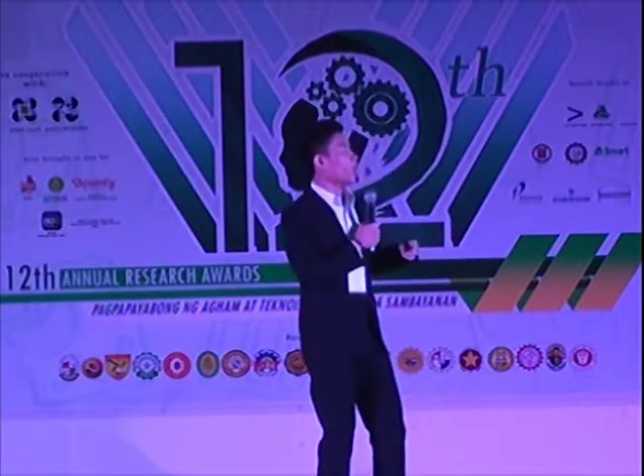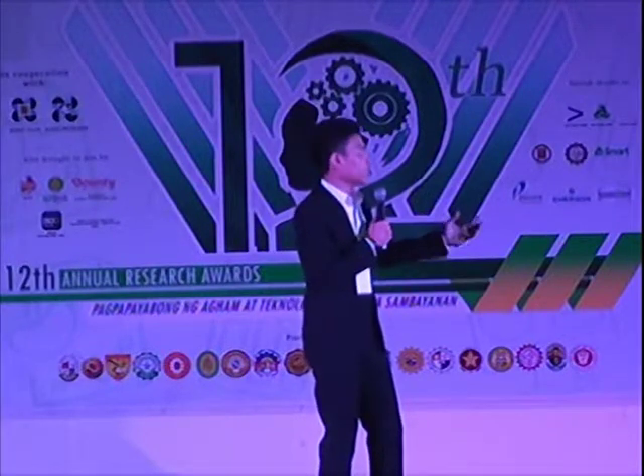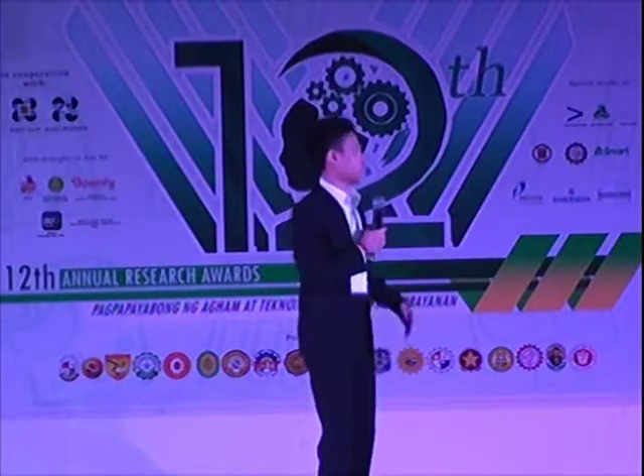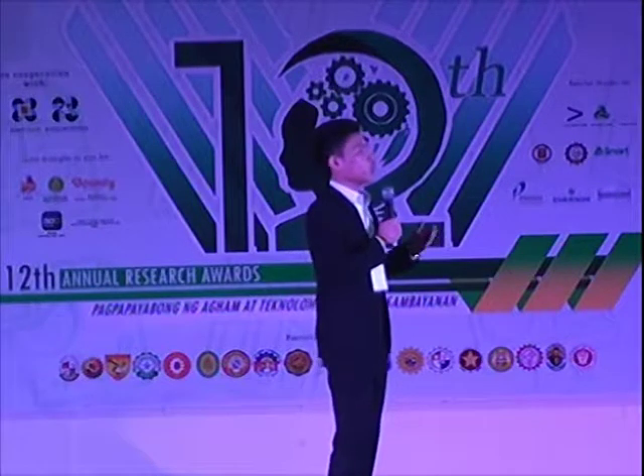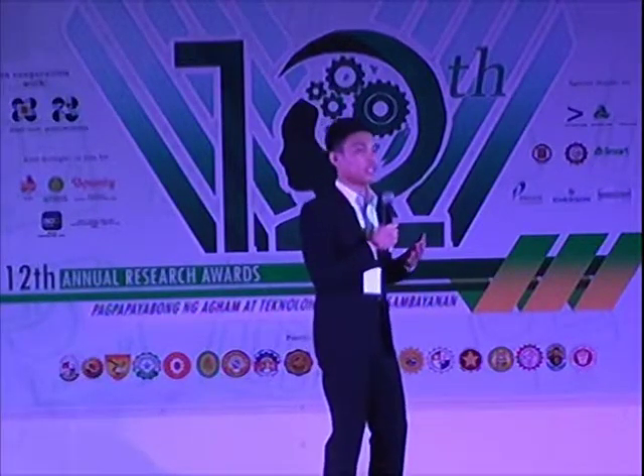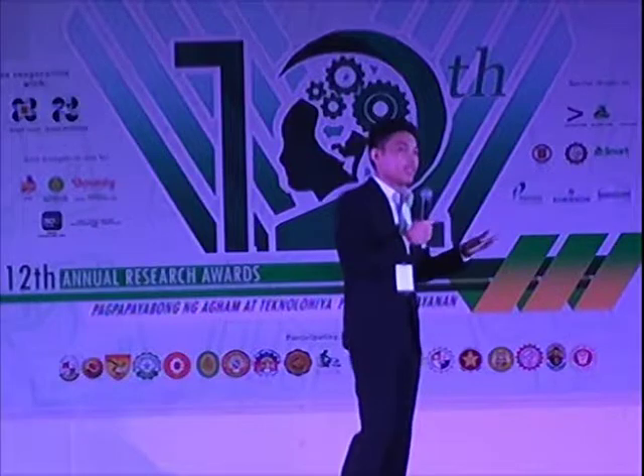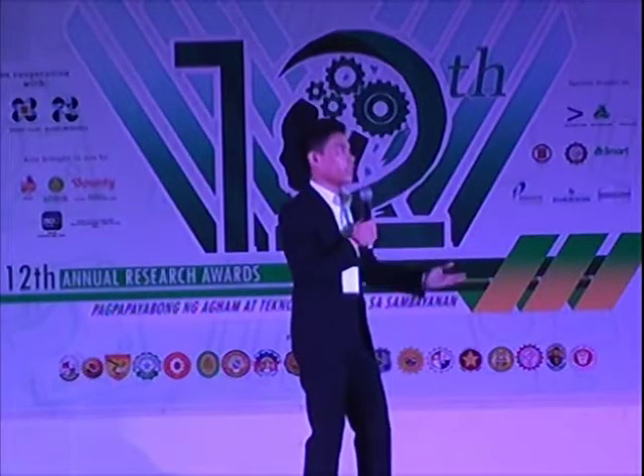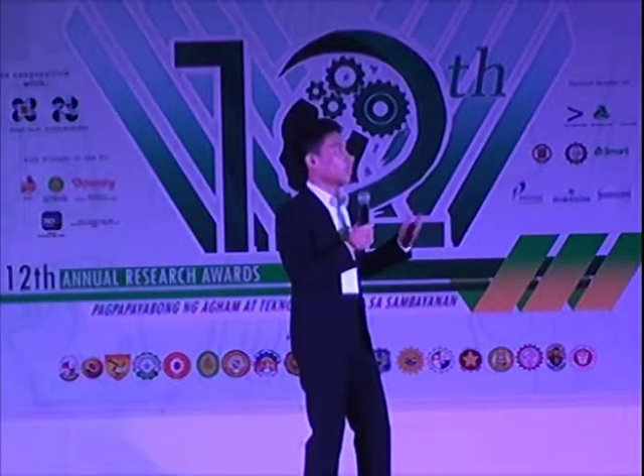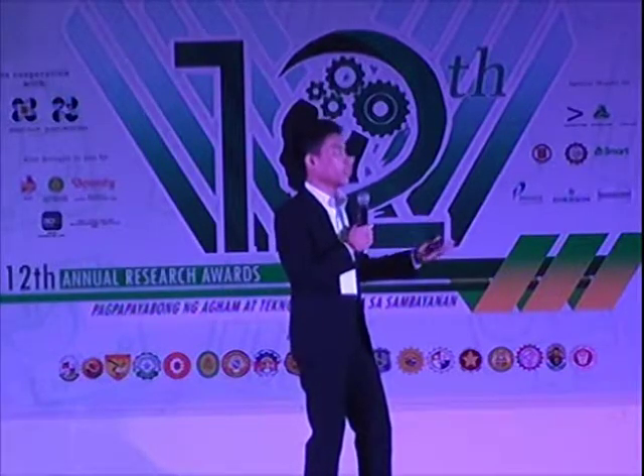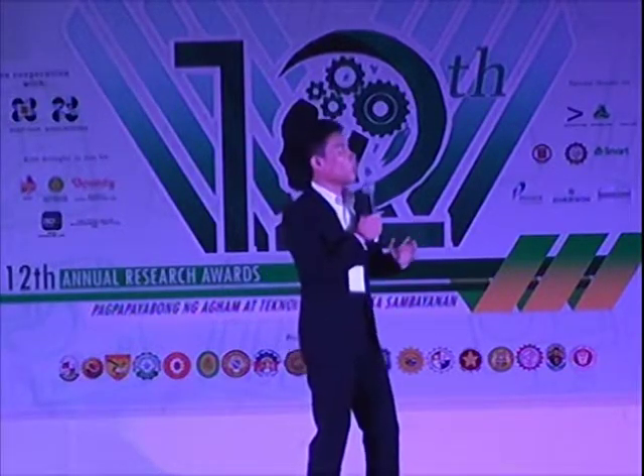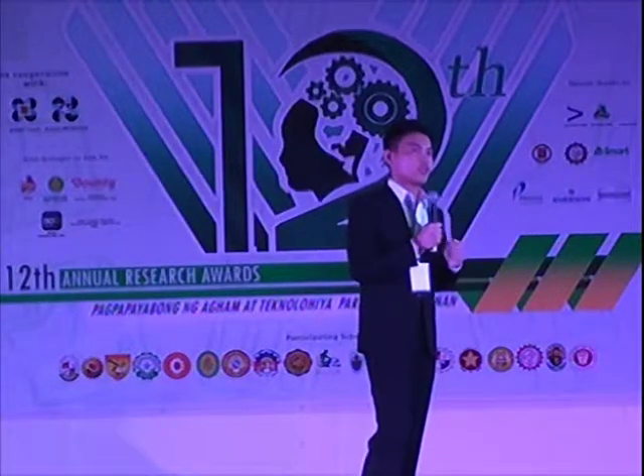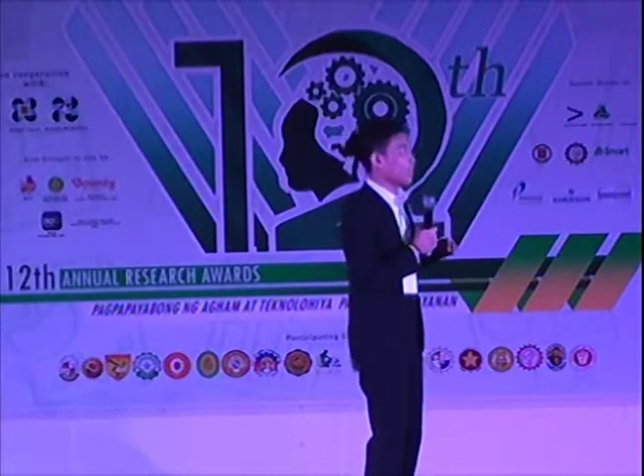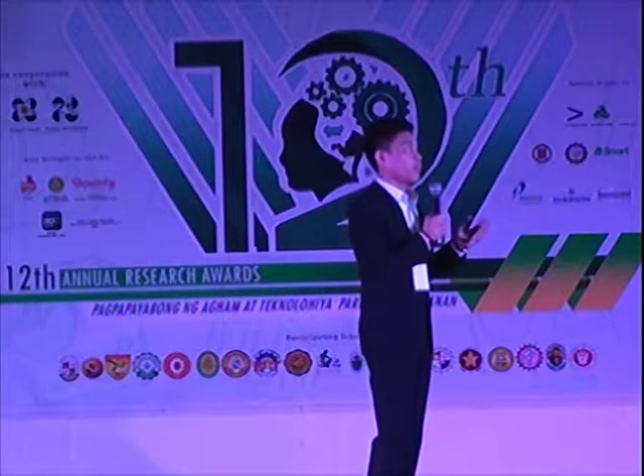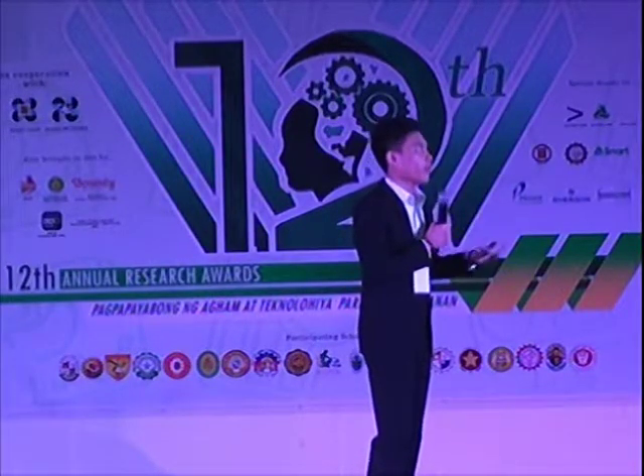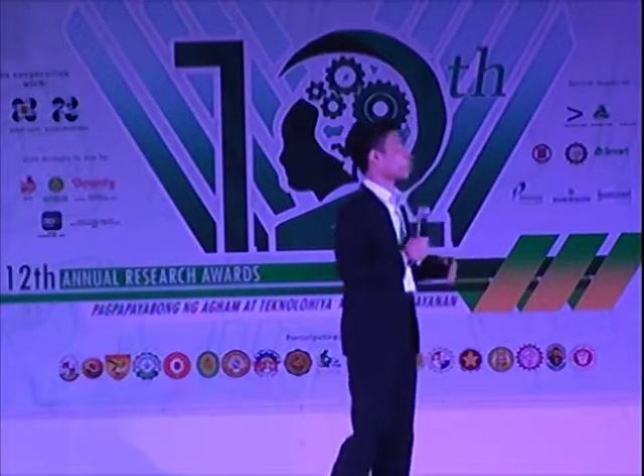Now we have two main groups of concrete samples, the A samples and the B samples. The A samples are already published in literatures. Basically, we're just repeating it. The percentage replacements are referenced from these literatures, 0.5% and 2.5%. By the way, the percentage replacement is in terms of cement weight. So basically, we have 99.5% cement and 0.5% NMT.